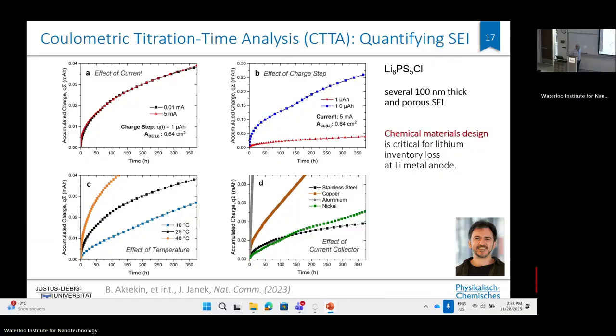And copper, that is considered not to alloy with lithium, takes up quite some lithium. This is not so well known, but it takes up lithium. And meanwhile, I would say we have more studies of that. So copper is really taking up lithium. Of course, aluminum takes up a lot of lithium. In principle, stainless steel and nickel could be better current collectors. But on the other hand, in industry, nobody will quit copper because copper foils are a ready-made mass-marketed metal product. So I think that we rather have to see, is this really an issue or can that be overcome?